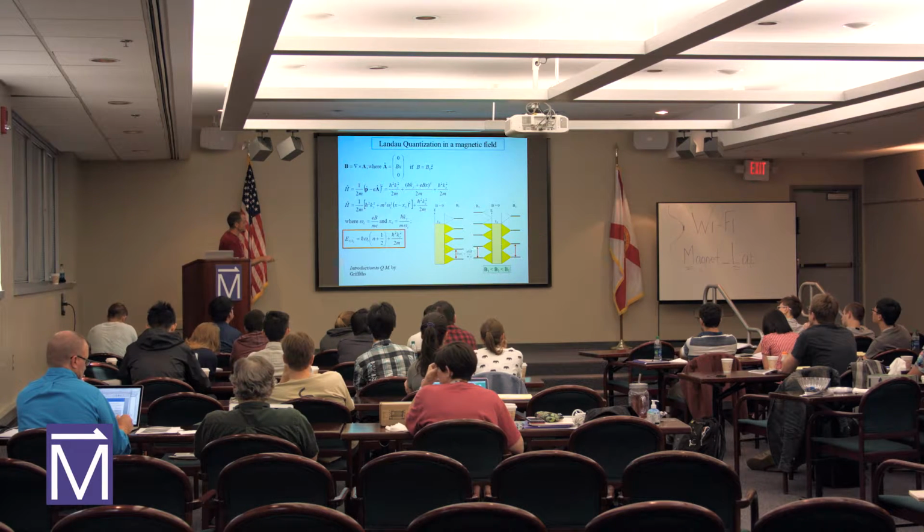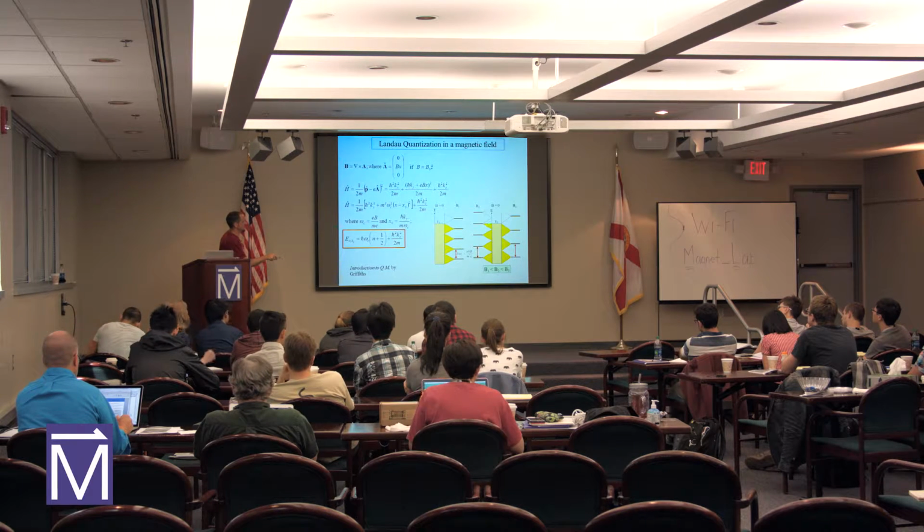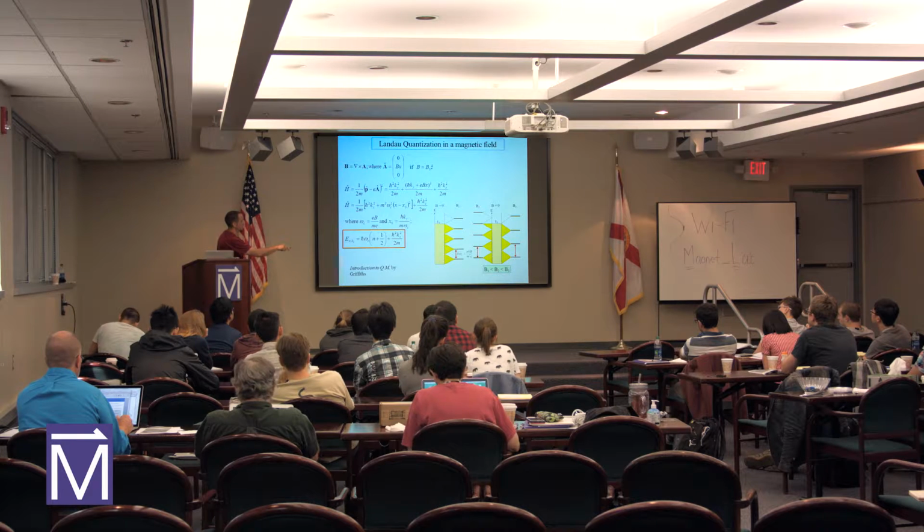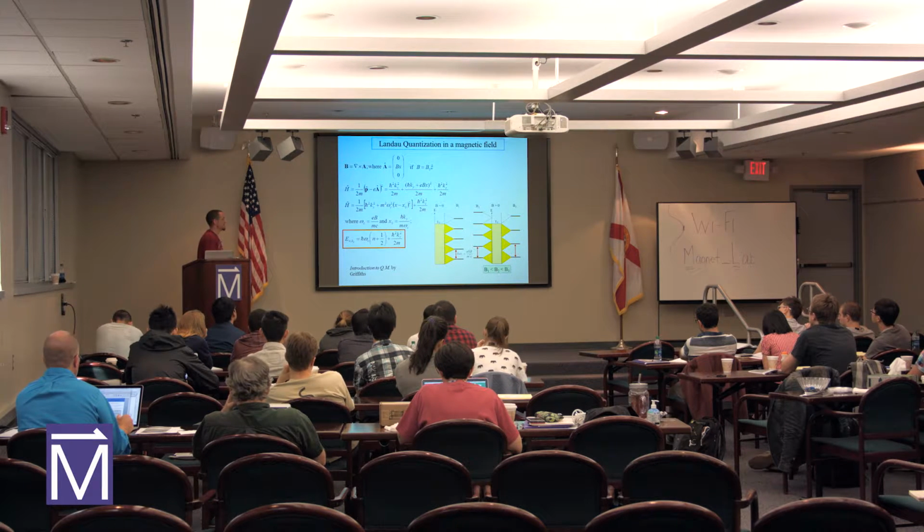When you increase the magnetic field further, these energy levels start to shift up and then past the Fermi level. As these energy states pass the Fermi level, you get a quantum oscillation. When the level gets past the Fermi level, the carriers fall back down into the next energy state. So as you sweep the magnetic field, you see oscillations in sample resistance, magnetization, et cetera.